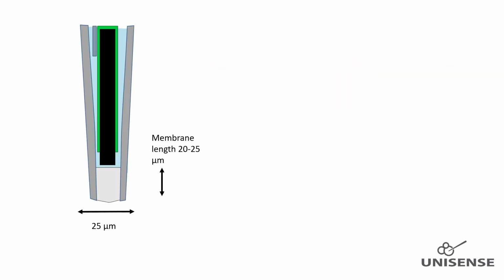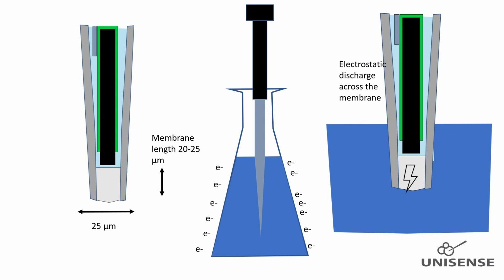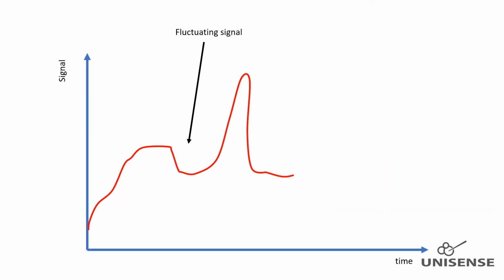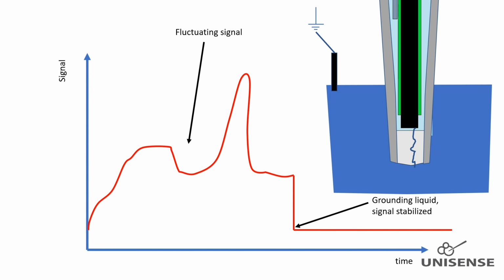The nitric oxide sensors have thin membranes, which can be vulnerable to electrostatic discharges. A charged person who touches, for example, a beaker in which the sensor tip is placed, can induce a potential difference of thousands of volts across the membrane and potentially induce a discharge which destroys the membrane. To be sure that this does not happen, a grounding wire should be connected to the liquid or setup in which the sensor tip is placed to the ground socket of the Unisense amplifier. A sensor with a damaged tip membrane will have a very unstable signal, strongly affected by electrical noise. By grounding the sample or experiment to the ground socket of the amplifier, the signal will stabilize. A damaged membrane cannot be repaired.